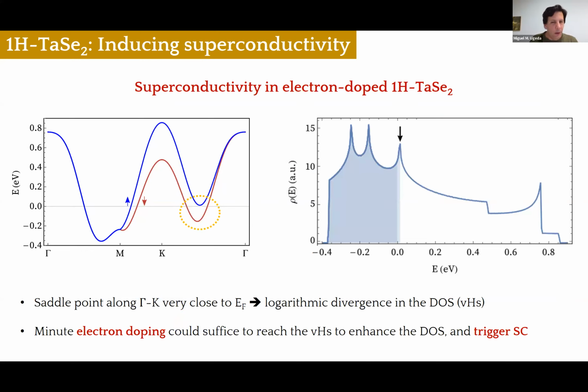Okay, but if you look carefully at the band structure, actually there is a trick to induce superconductivity in tantalum diselenide. If you look at this particular region between the K and gamma point, you will see that one of the spin split bands is very close to the Fermi level. So we are very close to a saddle point at the Fermi level, which represents a logarithmic divergence in the density of states. So perhaps if we add a minute electron doping in the system, we will be able to reach this Van Hove singularity, enhance the density of states, and therefore trigger superconductivity.